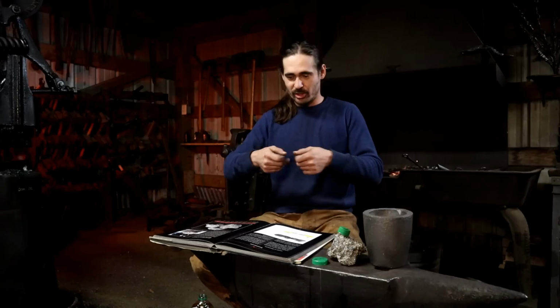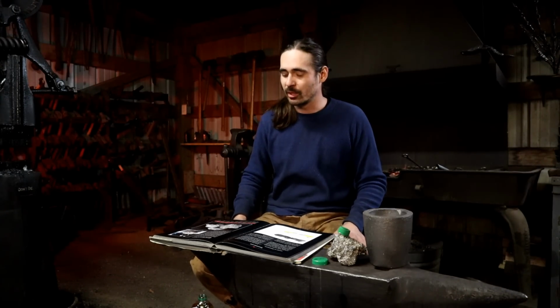What that means is, tamahagane, once it's properly processed, that is folded a bunch of times, and you reduce carbon, remove some of the impurities, so the slag will just melt away as the slag acts as flux, and often enough, you don't even have that much slag to begin with. The end resulting bar of steel that you have tends to be superior to the crucible steel bar.